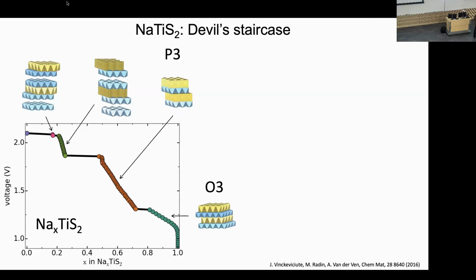And then the P3, this is where the sheets have had to undergo a glide transition. They glide, and that shears the sites that sodium can reside in, and they become prismatic. So these are prismatic sites, and that's where the P comes from. What you see is, because sodium's bigger, when you start with this O3 stacking and pull sodium out, you create vacancies, and then this stacking sequence becomes unstable. It wants to undergo a glide transition, and you form this prismatic stacking. And that's stable over this region. So you have a two-phase reaction to go from this stacking sequence to that one. Then if you continue taking out sodium, you get staging, where you have mixtures of empty and P sites and so forth, and you get a sequence of other phases.